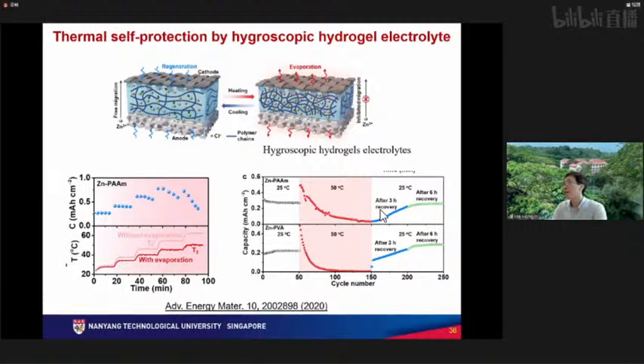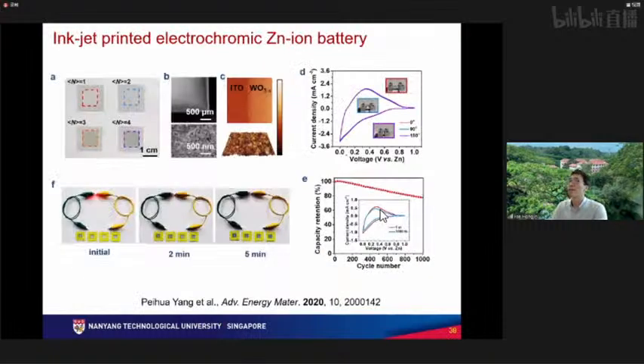And then if the temperature goes back down to 25 degrees, it takes 3 hours, or even 6 hours, to recover. Of course, this recovery time is too long. You don't want to wait 6 hours. But it's a proof-of-concept demonstration. If you better design the polymers and better design the packaging of the cathode and anode, maybe we can have better, higher recoveries. And then we can also make printable zinc-ion batteries.